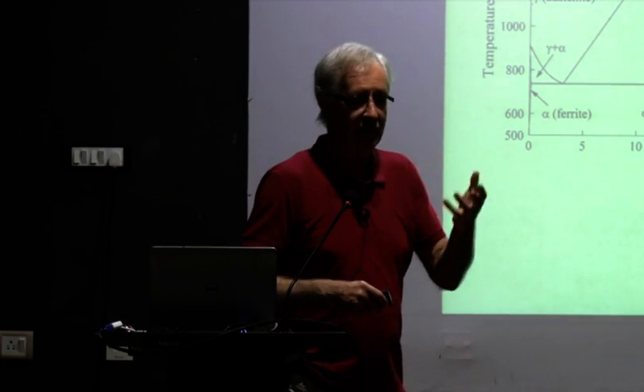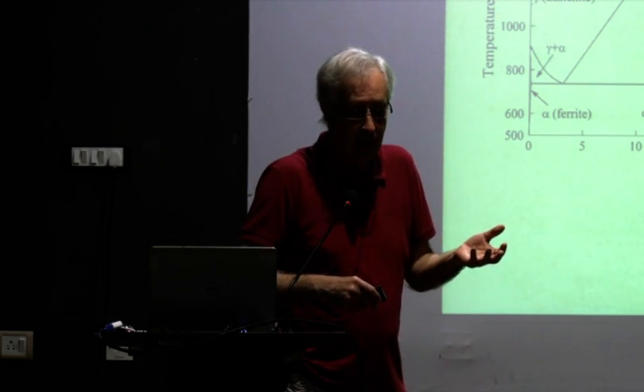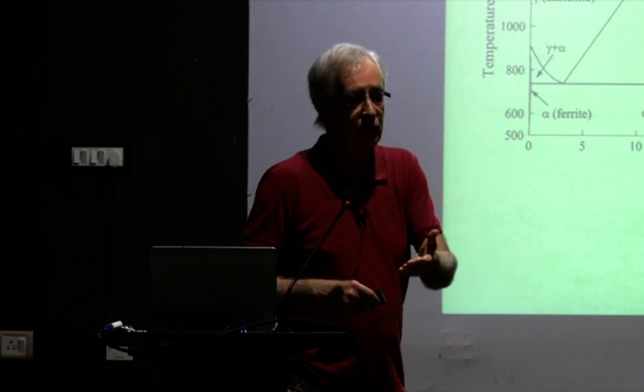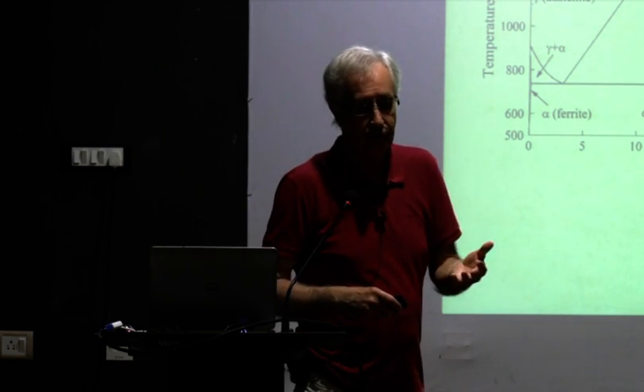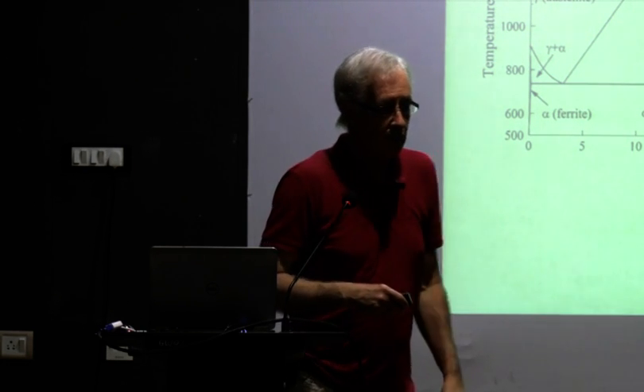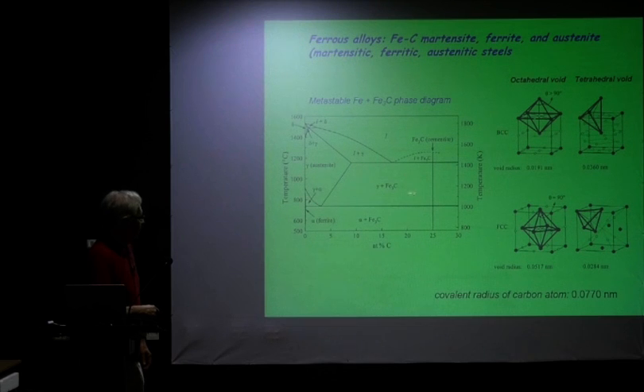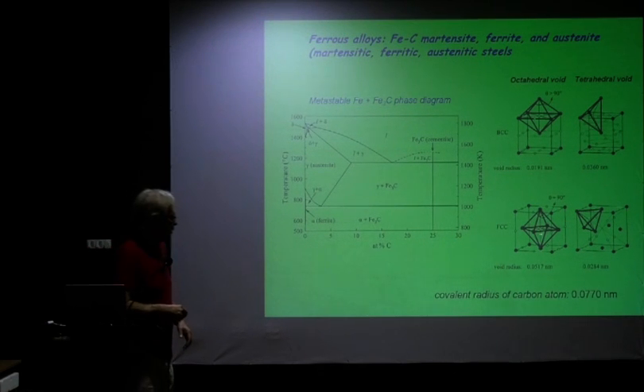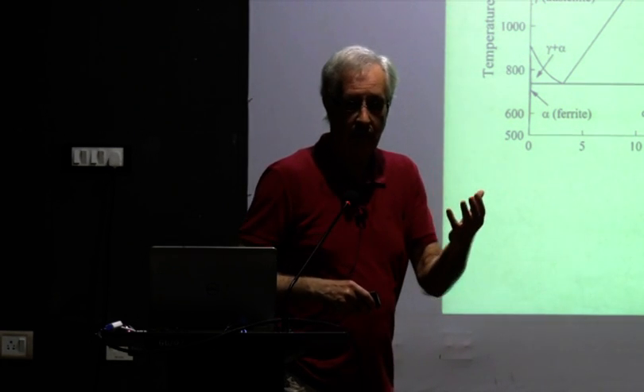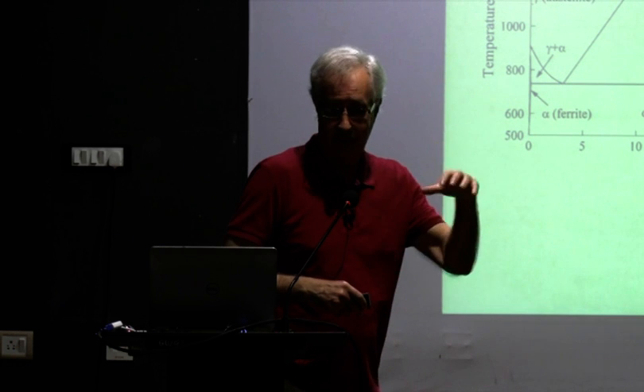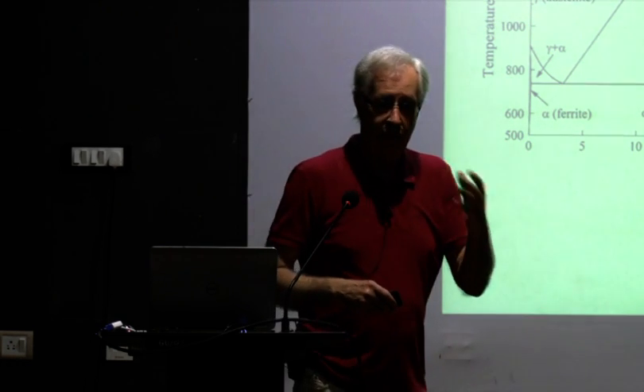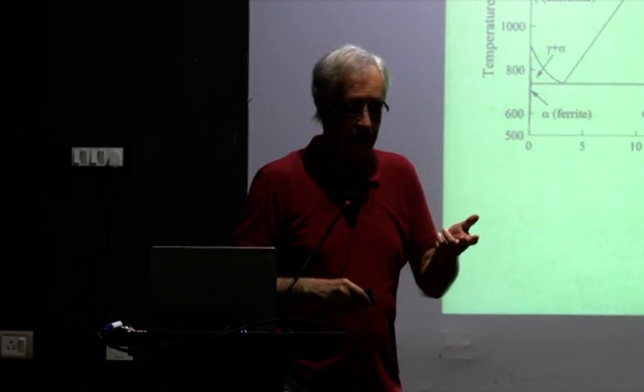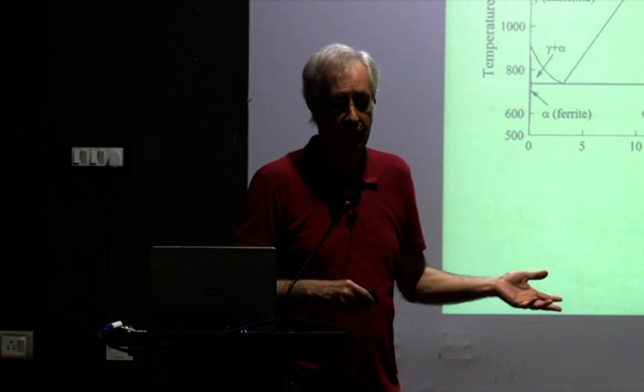Ferritic steels. Ferritic steels means body-centered cubic steels. It has come to be known that, for example, iron chromium is a ferritic steel, okay? Any steel that remains in the body-centered cubic state. If you are in the austenite state, then you have this structure, and if you quench this very rapidly, then you will have carbon trapped in here, and you get a retained austenite. You have the FCC state, so to speak, stabilized at low temperature. And these are known as the austenitic steels. So the austenitic steels are face-centered cubic, and the others are body-centered cubic.